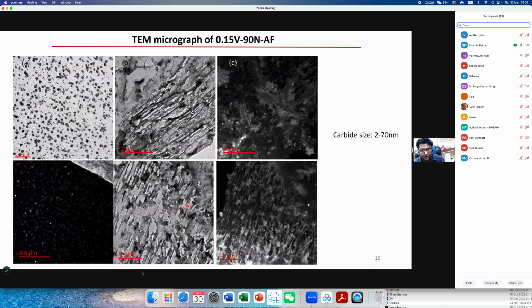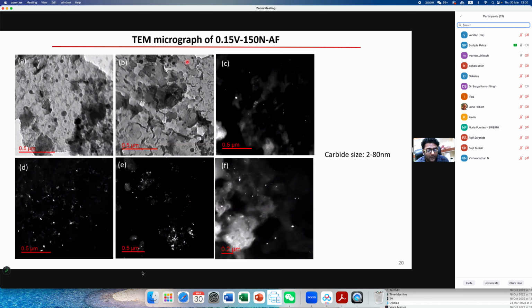Okay. So in case of 150 nitrogen, the precipitation concentration actually decreased a little bit. There are some fine precipitates inside, but some precipitates are around 80 nanometer, coarse and spherical. Here we did not observe that. And also some precipitate clustering we observed here in the extraction replica. Inside the pearlite also some precipitates we observed. But we could not confirm with EDS, as EDS was under maintenance.